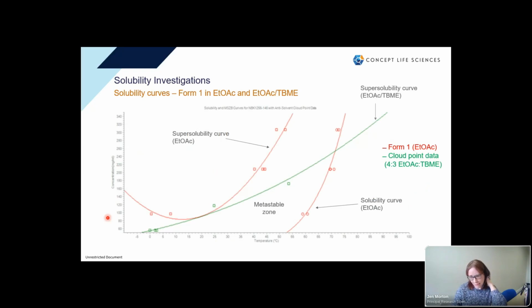So the last piece of work we did in the Crystal 16 was to look at our original antisolvent recrystallization. Now, we'd had a bit of difficulty repeating this exactly in the Crystal 16 because once we'd added our antisolvent and the material had crystallized out, we were never able to get it to go back into solution. So we couldn't do the temperature cycling that you saw on one of the slides that Carmen showed. But we were able to dissolve our material in ethyl acetate, as we had done in the original process, and then add some antisolvent to the vial, put it back into the Crystal 16 and continue with the cooling ramp and allow the Crystal 16 to detect the cloud point.